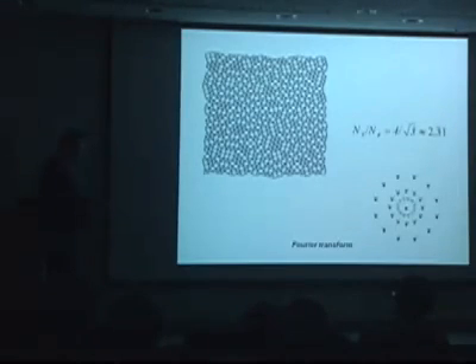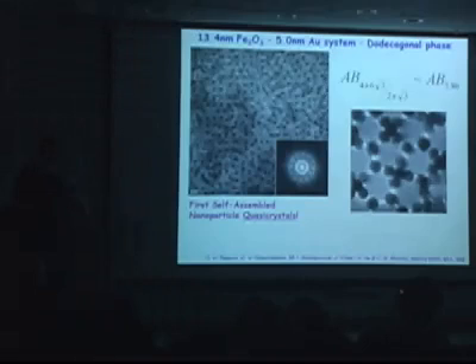So now we have a long-range ordered structure, we have a forbidden symmetry element, and we have no translational symmetry. And all this can be plugged into nanoparticles. That's how we made the first structures. This is a self-assembled nanoparticle superlattice, and this is its electron diffraction pattern with 12-fold rotation symmetry, and this is the stoichiometry, a rational stoichiometry. Kind of a bit weird.